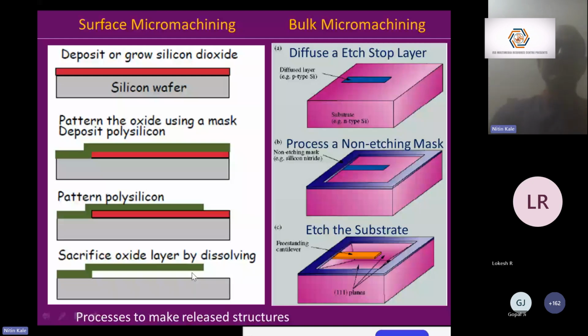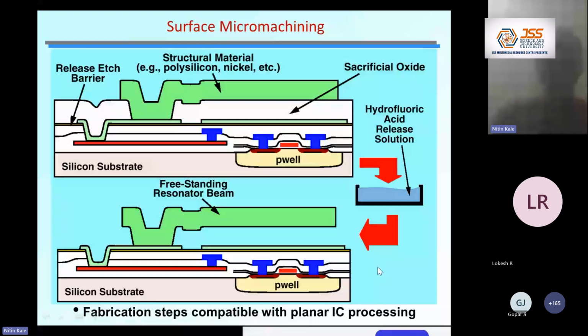In bulk micromachining, rather than a sacrificial layer, you sort of dig a hole in the ground, let's say. So in your substrate material itself, you are digging a hole. So this is your substrate material. This is the structure of your interest. After masking, etc., you have kept it like this, and you have dug in the substrate. So you can have a freestanding structure which is capable of movement, and you have dug a hole beneath it. So these are two different approaches of micromachining, so that you can free a mechanical structure. This is some sort of a cartoon which explains how it is done. Generally, hydrofluoric acid is used to etch away the sacrificial oxide.